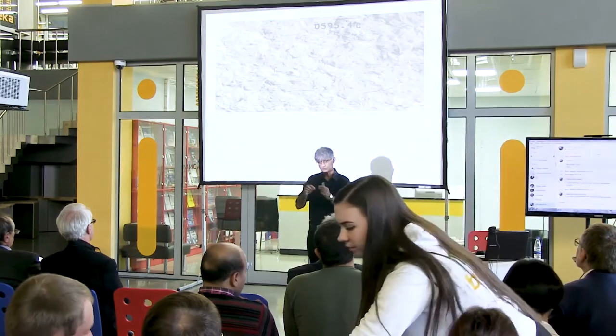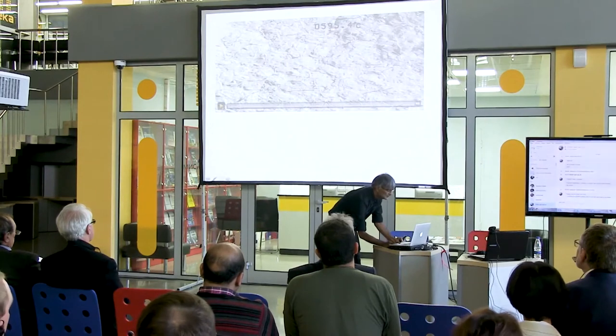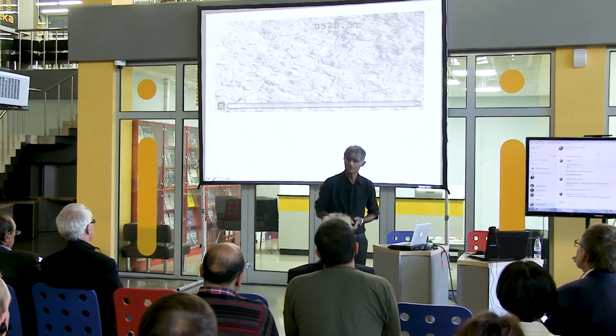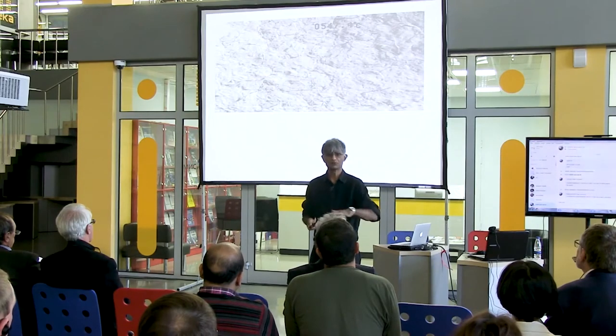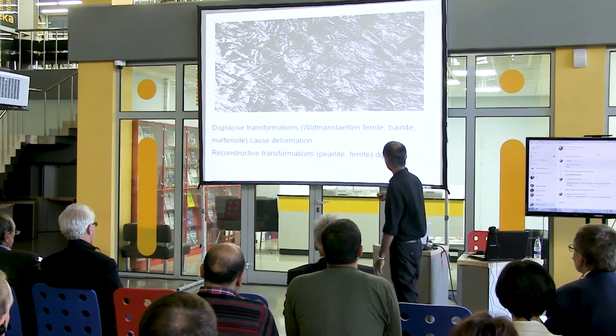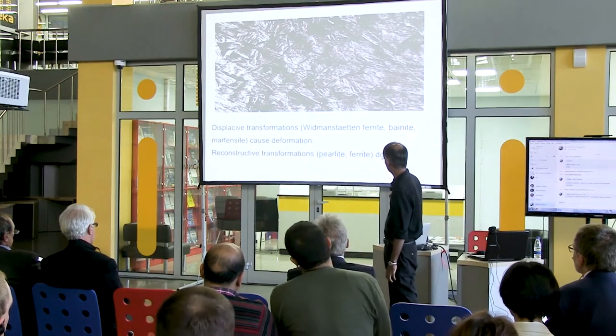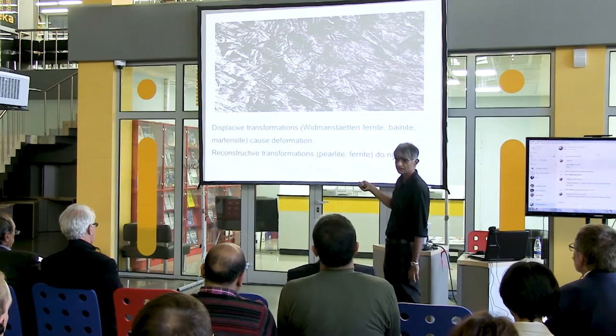In contrast, when we form those thin plates, just keep watching this movie and you'll see massive changes in shape on the surface of the sample. This is like the formation of a range of mountains. The deformation is very large, much larger than elastic strains. That is what gives us a very fine grain structure. In steels, you get a variety of transformations. This is bainite producing a change in shape, whereas ferrite and pearlite result in very boring movies.